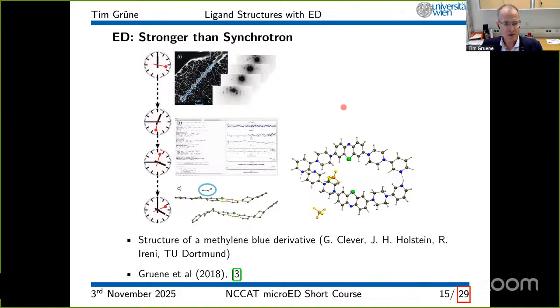This structure that we solved here, the data collection itself took about 45 minutes. And this was mostly because it was really a hands-on experiment. Everything that we did at that time was not very automated. We processed the data within 4 hours because I had to do it one by one and very carefully. But the structure solution was done like with X-ray data. It took 15 minutes to solve the structure, and the refinement was also very quick.